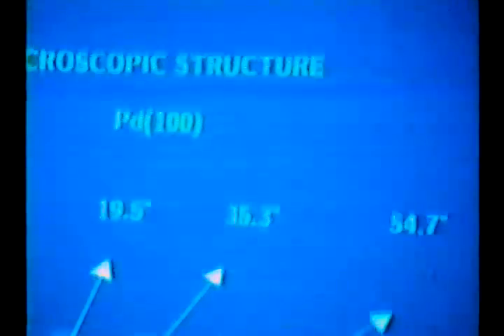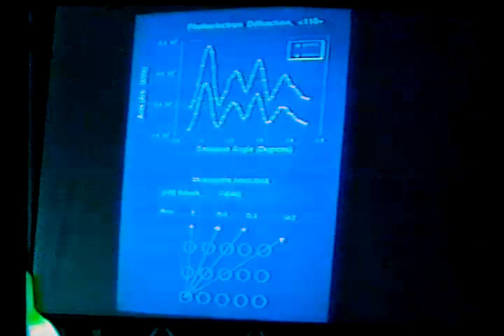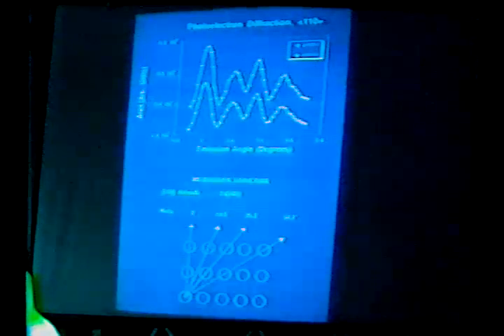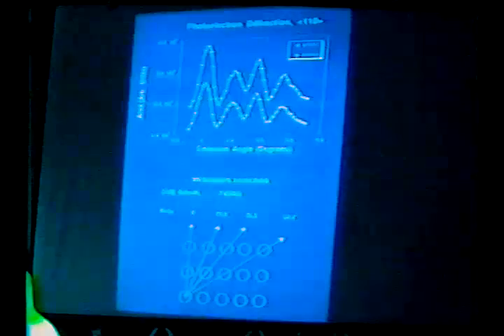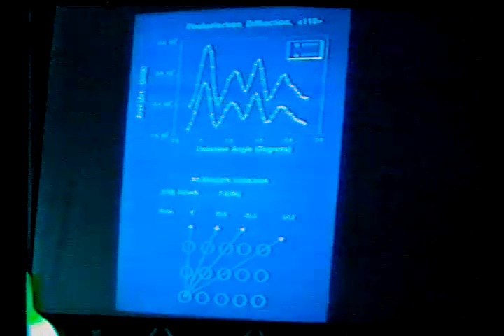Here is a diagram that shows, again, I stress, with high energy resolution, because this would be important in characterizing chemisorbates. When the emitter is a subsurface atom and the scatterer is a surface atom in the first layer, you can see that there is a distance here for the scattering event that goes back to the second layer. There are in fact some emissions that go back to the third, fourth, fifth layer. Then there are, of course, also scattering phenomena where the second layer atom is scattered off the first layer, but the path lengths are not equal for those events. And here is an experimental curve that shows that these scattering directions have been observed quite accurately to within approximately 1 degree, which translates in this experiment to 0.02 angstroms in unrelaxed palladium.